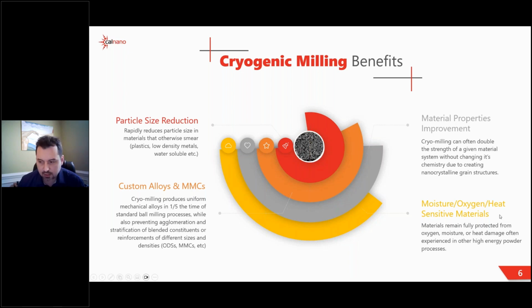Some materials can be processed relatively easily, but they're just particularly sensitive to moisture or oxygen. There's usually some other options as far as processing, but again, given that we are in a liquid nitrogen slurry, there is zero chance of any oxygen absorption coming in. And the localized temperature increases that are the result of the grinding are kept very, very low given the cryogenic environment.